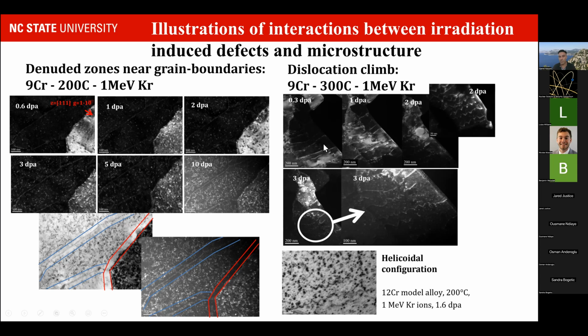You can see in the beginning on those pictures the straight lines typical of the dislocation lines that you have in this martensite structure, very straight. Very quickly, after less than a dpa, in fact, you start seeing how these straight dislocation lines are affected, and they start having this zigzag shape. It doesn't matter the material, 9 chrom, 12 chrom, we see the same type of process. And that is basically the testimony of the interaction of the defects with those dislocation lines.